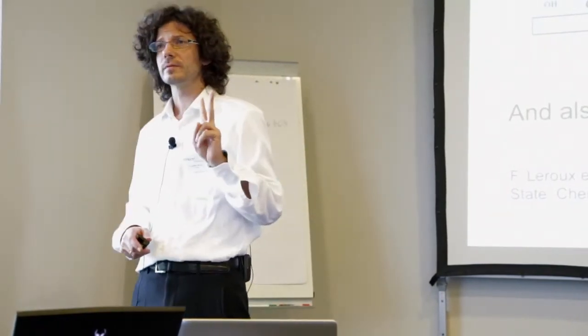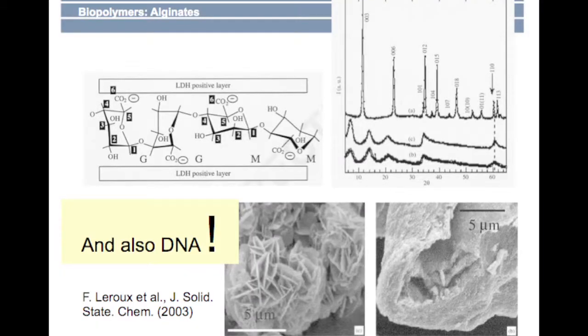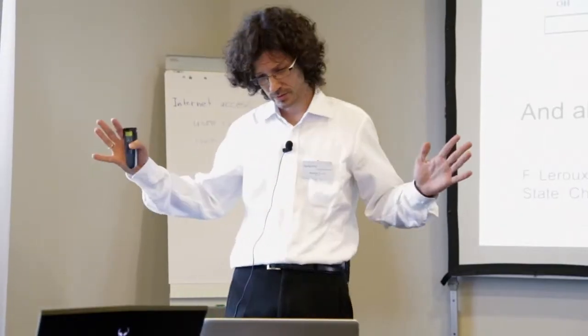Now, there's two important things to emphasize here. First is, as you increase the size, you tend to lose a little bit the nice X-ray signals. You get a lower angle peak appearing, which corresponds to the larger layer spacing. And very large molecules as DNA, you can produce these structures if you do it in an one-pot reaction, meaning that the precipitation of your phase takes place in the presence of the organic additive. If you add it afterwards, it won't happen when the molecule is very large.